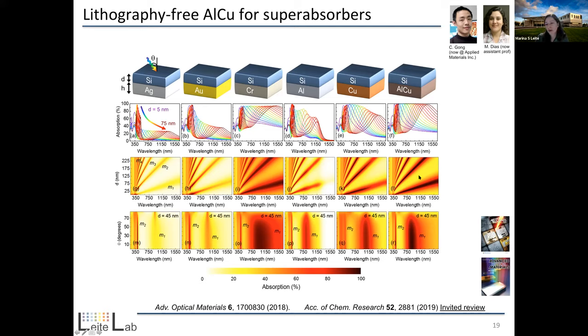So we can focus here on the last row, where you can see these very well-defined optical modes and how high their absorption is. A very dark color here in our scale means a really high absorption. And you could also see that as a function of angle, theta here. So now theta is the angle that defines the incidence of light with respect to the normal. We could see that up to 60 degrees, we still had a quite robust type of response.